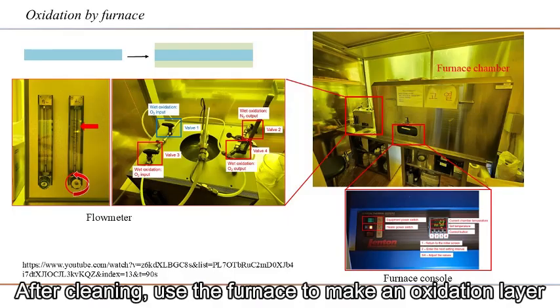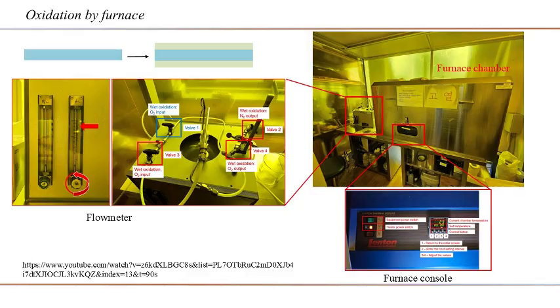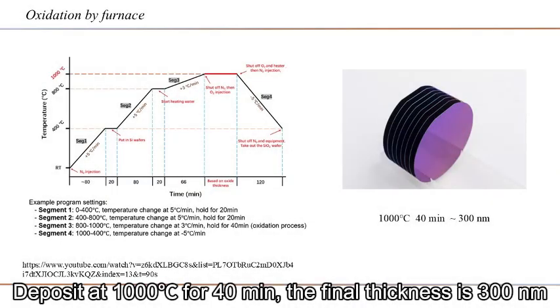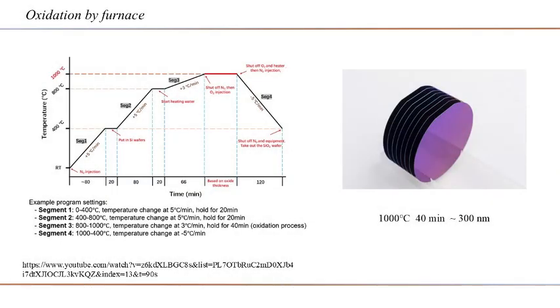After cleaning, use the furnace to make an oxidation layer. Deposit at 1000 degrees centigrade for 40 minutes. The final thickness is 300 nm.